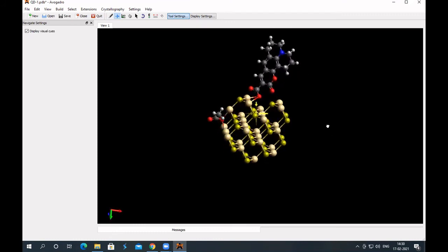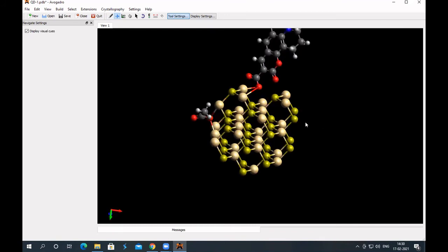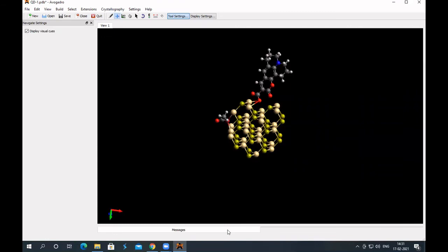And then slightly you can modify it. So this is the procedure to obtain a passivated dye-sensitized quantum dot. Again repeat, you have to count the number of cadmium ion and sulfide ion, and the difference in the charge should be balanced by some co-ion. So there's more positive charge then use acetate ion. There's more negative charge then you can use positive ions like methylamine or H-positive ion. And this is how we passivate them. So I think play with this, try to model the system which we have published that has cadmium-16, sulfur-13, and then four acetate ion, that was one model, or with three acetate and one dye.